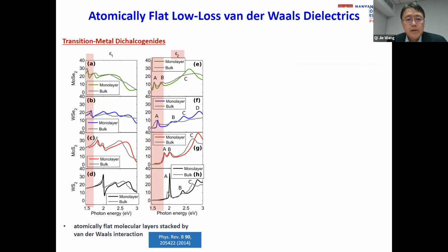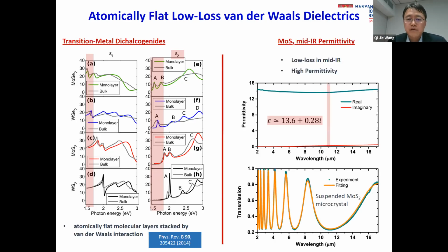And the loss of 2D material in the mid-infrared remain unexplored. However, in the literature, there are already some detailed studies that investigated the property of the 2D material in the near-infrared regions. So here, for example, it shows that many 2D material has a relatively low loss in the near-infrared region, which also show the trend into the mid-infrared region. The imaginary permittivity should approach 0.